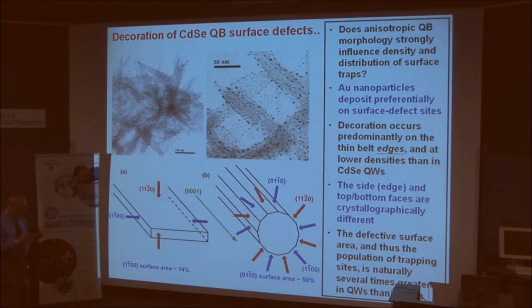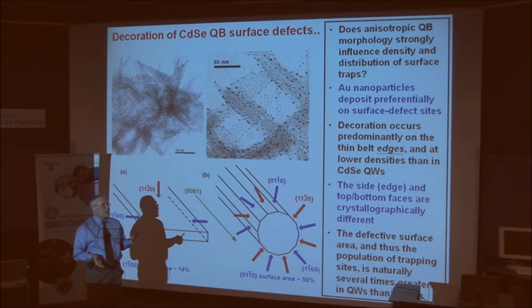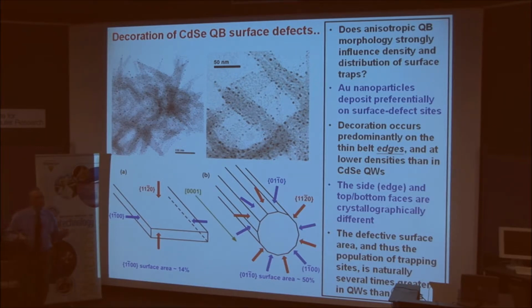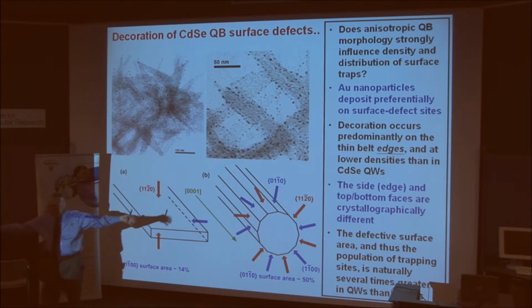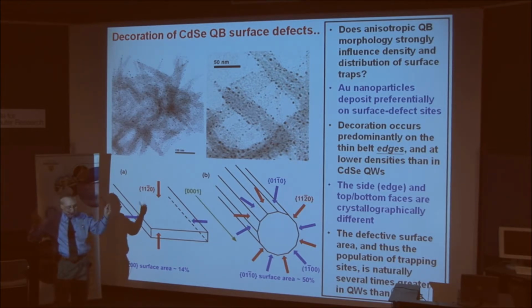Okay, we thought that there must be something interesting about the population of defect sites on these belts that might justify why their optical properties were so much better than those of the pseudo-cylindrical wires. And so to try to identify this population of defects on the belts, we did a decoration experiment. The strategy behind a decoration experiment is as follows. If we're all looking off into the distance at some telephone wires, if the poles are far enough away, we can see the poles, but we can't see the wires, until a flock of crows comes along, and the crows sit down on the wires and decorate the wires. And now we can sort of see the wires because we can see the crows. We know where the wires are because the crows have decorated the wires. And that's the concept behind a decoration strategy here.